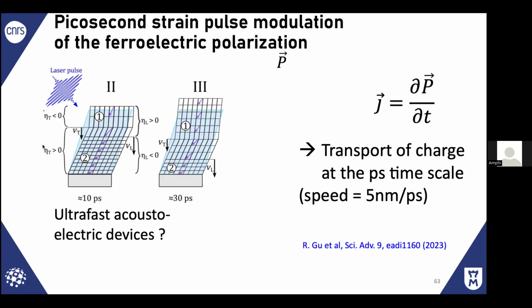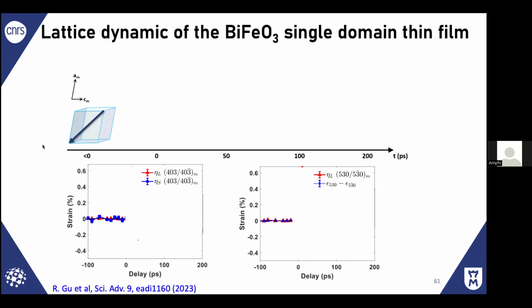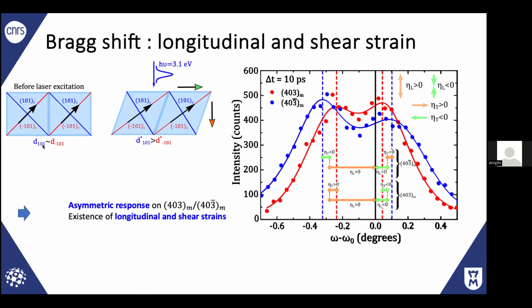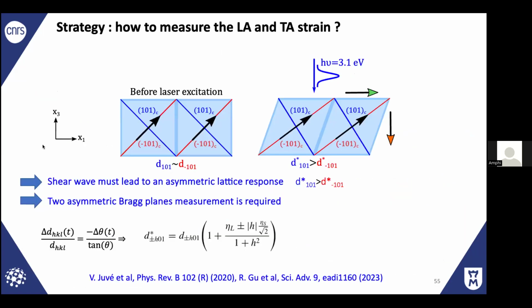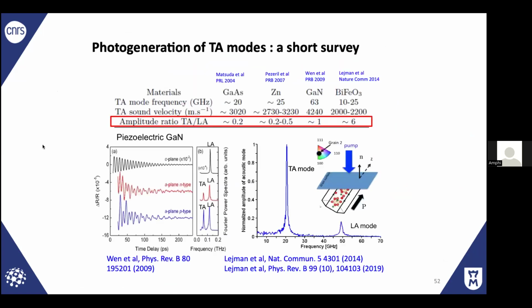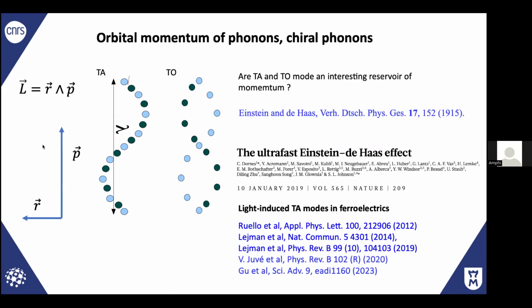I think torsion will lead to relation to the shear motion. If you want to induce torsion, it's exactly the same way that when you create a circular polarization with light, you combine two transverse electromagnetic waves, like the ordinary waveplate. So if you are able to generate two kinds of transverse acoustic wave, but in two perpendicular polarizations, and you control the phase, then you can create, say, a circular transverse, circular strain.